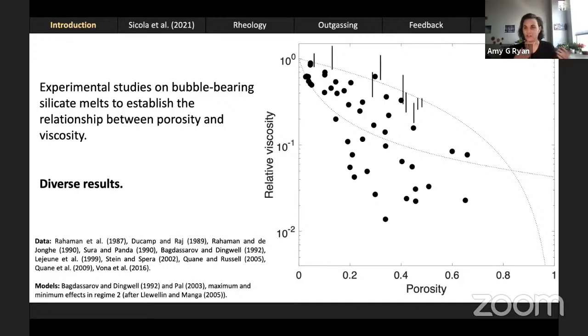As such, there are numerous experimental studies that have been conducted to try to constrain the relationship between porosity and relative viscosity for silicate melts. But you'll note right away that we have diverse experimental results. At the most extreme, materials of the same porosity have measured viscosities that are 2 orders of magnitude different across studies. I've also plotted on here 2 semi-empirical models, and you can see in some cases they do a good job of describing the data, and in some cases they don't do a great job, and in some cases they're entirely unconstrained. So I want to take a first crack at trying to understand why we're getting these diverse results. And I would suggest that we do that by thinking about the pore geometry in the materials that have been used in these experimental studies.